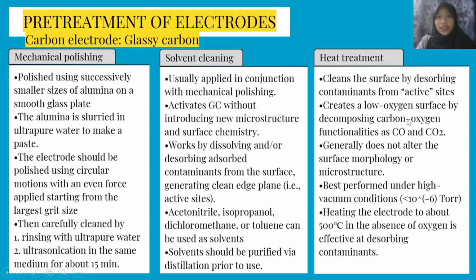So the third one here is heat treatment. The heat treatment cleans the surface by desorbing contaminants from active sites, and it creates a low oxygen surface by decomposing the carbon-oxygen functionalities as carbon monoxide and carbon dioxide. It generally doesn't alter the surface morphology or microstructure, and it is best performed under high vacuum conditions in these